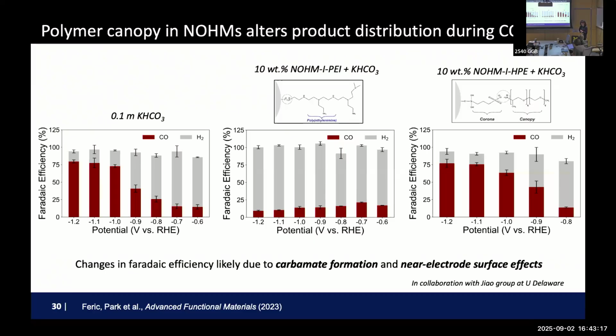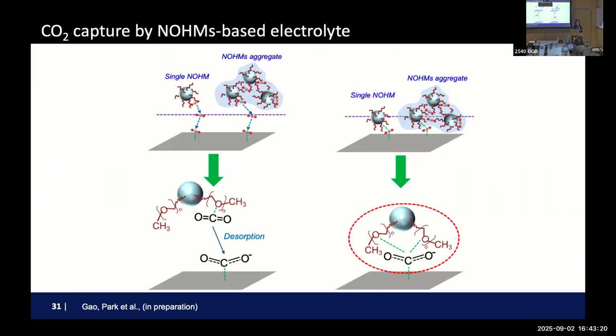So we start to think that, well, somehow, although we use exactly the same catalyst, it wasn't going through exactly the same reaction pathway. In fact, if you look at what NOHMs are doing in the system, they can deliver CO2 to the bulk and release that CO2, especially if there are NOHMs with ether groups, and that released CO2 will be phase-dissolved onto the surface of the catalyst. In that case, your Faraday efficiency should not change, right? Current density might, but not Faraday efficiency. But we did change the Faraday efficiency, which means that in some cases, NOHMs actually deliver CO2 to the surface, even the ether group ones. And then what happens is at the surface of the catalyst, when CO2 gets absorbed to the catalyst, the ether group surrounding it was bending CO2 just a little bit and changing the way it was reacting. So now we can start calling it maybe a co-catalyst. So there's a lot of design we can do.